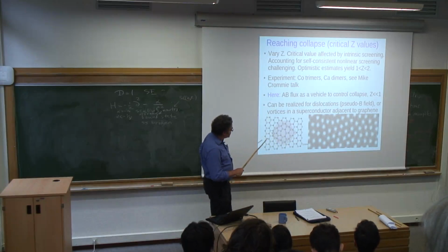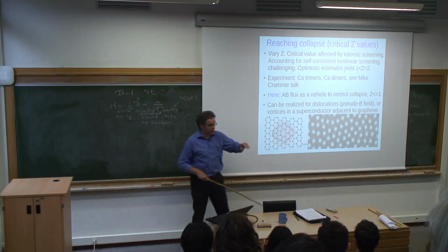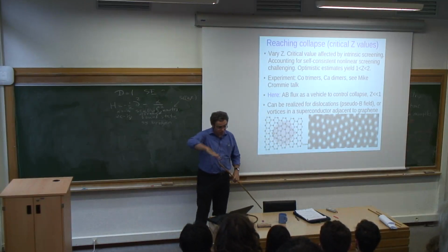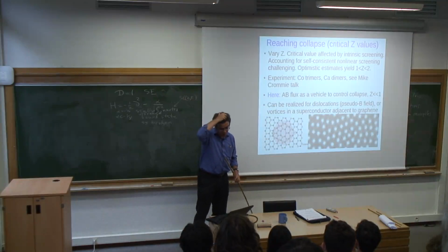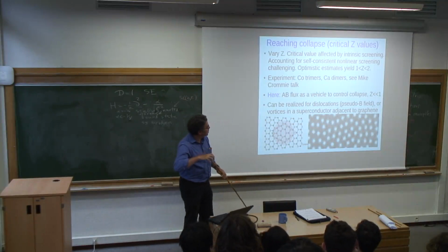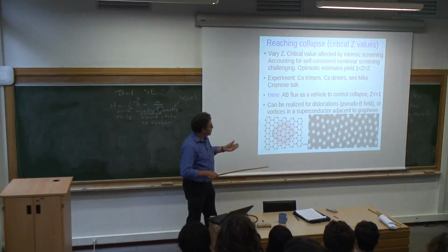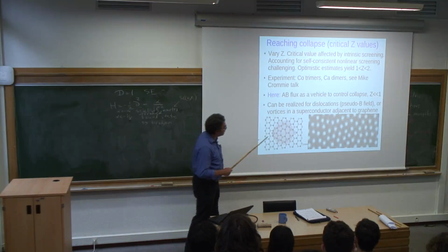In particular, if you take graphene and find a dislocation in it, there will be a strain field around the dislocation, and just like you said, the strain field will produce some pseudomagnetic vector potential that will correspond to some Aharonov-Bohm flux value, which is purely geometric. One can evaluate it using the Burgers vector of the dislocation and show that it's equal to plus or minus a third of the flux quantum.